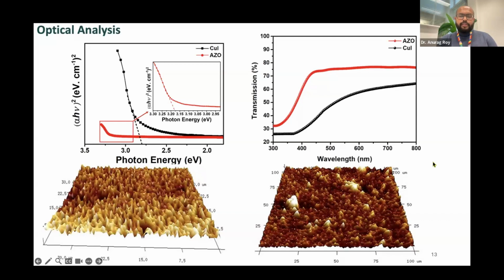You can see the visible optical transmission data, and next is the AFM, which is another parameter to understand the surface roughness and at the same time the thickness. So roughly here you can see the thickness is more or less the same for both. This is the aluminum doped zinc oxide, and this is the copper iodide thin film, AFM cross-sectional area.